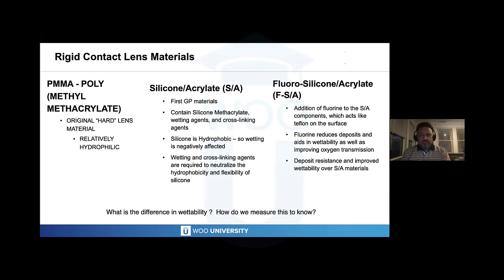So the silicone implementation was important, but it had wettability issues. And so the addition of fluorine into the process, or the fluorosilicone acrylate, which is what most GP lens materials are nowadays, the fluorine helps with wettability of the surface, and it also helps resist surface deposits in the process as well. So again, most of the materials you probably would order for your patients today in 2021 are going to be the fluorosilicone acrylate family of materials.